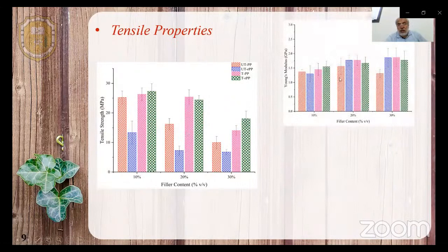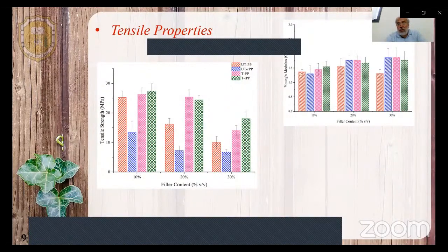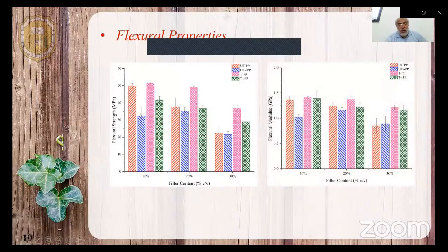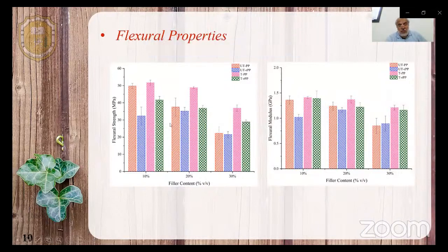For the Young's modulus, we can see here that there is an increasing trend as we increase the filler content. And also here we can see that for recycled and virgin PP based biocomposites, the results are comparable. When we looked at the elongation at break, we can see that as we increase the filler content, the material becomes more brittle. For the flexural properties, the improvement due to the treatment was more pronounced, but a similar trend compared to the tensile strength was observed here. Okay, but more improvement, as I mentioned.